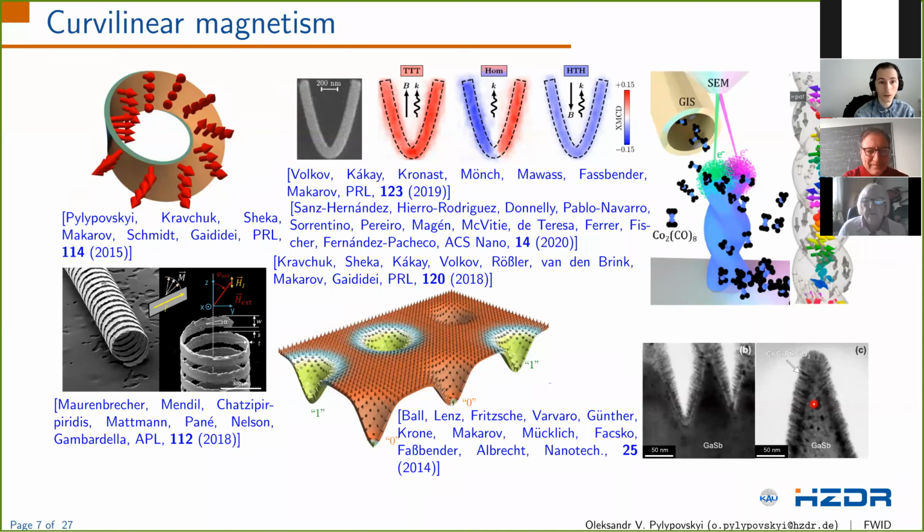First of all, this is geometry-driven symmetry breaking, leading to stabilization of chiral domain walls at curvatures, even for intrinsically achiral materials. The geometrical chirality of the Möbius rings or spirals is intrinsically coupled with the domain wall chirality and the broken symmetry of the anisotropic magnetoresistance. Moreover, this can lead to the appearance of imprinted skyrmions as ground states in ultra-thin films. Modern technologies such as FEBID or FIBID allow creating nanoarchitectures of almost arbitrary shape at the micro and nanoscale. So, in other words, the approach of curvilinear magnetism opens a way to tailor the design, chiral and anisotropic responses even in intrinsically achiral materials. Another important consequence is to utilize the third dimension in comparison with conventional planar electronics, which opens new physics and effects in magnetism.